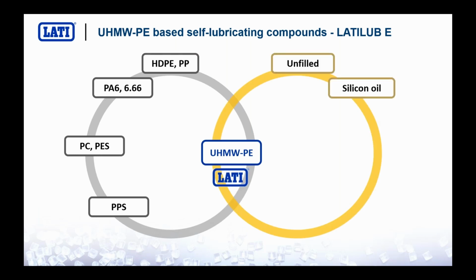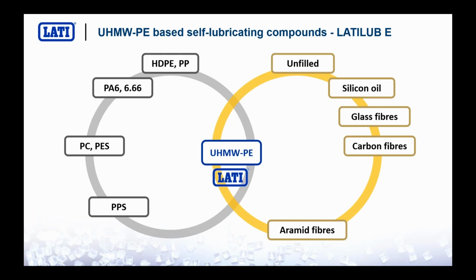Also from a filler point of view, we have been working with ultra-high molecular weight polyethylene in silicon, glass fibers, carbon fibers, and aramid fibers. Now we are working also with other synergies, but as you can see, the combination is much lower than the combinations available for PTFE. Also, the available maximum temperature of these self-lubricating plastics is lower. Why? Because we found out that it's very difficult to properly disperse ultra-high molecular weight polyethylene in high temperature plastics, so in PEEK or PPA or polyphenylsulfone and so on. It's very difficult to have a proper dispersion of this additive, and this leads to very poor performances as a self-lubricating additive.